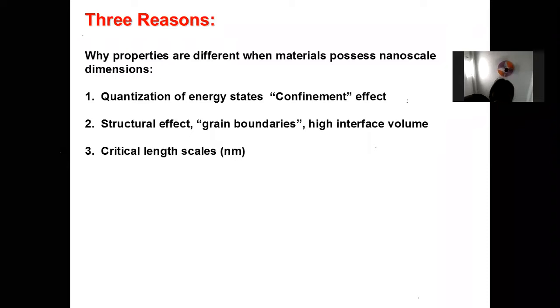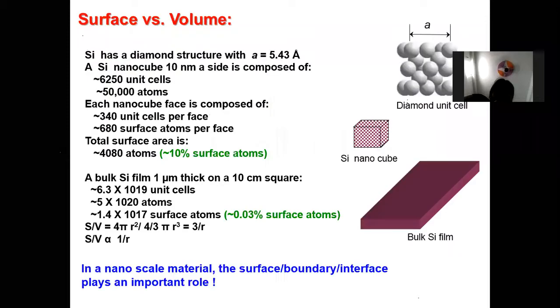Structural effect: if you have a bulk, then grain boundaries are there. The interface volume to surface ratio will be very high, and critical length scales, because we are in nanometers. Critical length means a few atomic units are there, so we don't have a large number of atomic cells. We have a very small number of unit cells. If you see there, I have shown the surface versus the volume. In the case of a silicon nanoparticle, 10% of atoms are at the surface. But in the same silicon in bulk size, only 0.03% of atoms are at the surface.